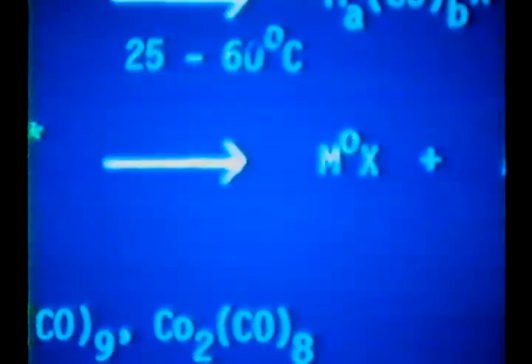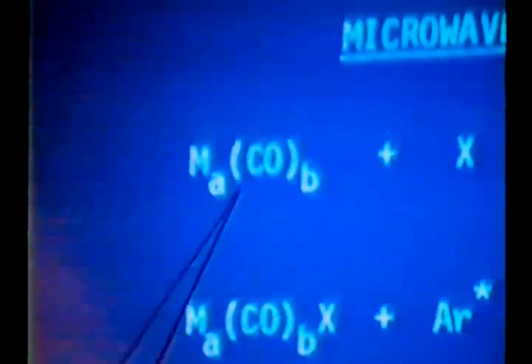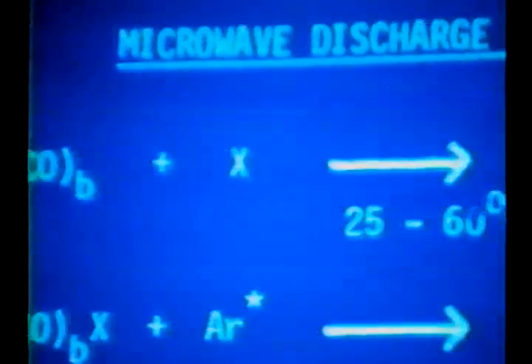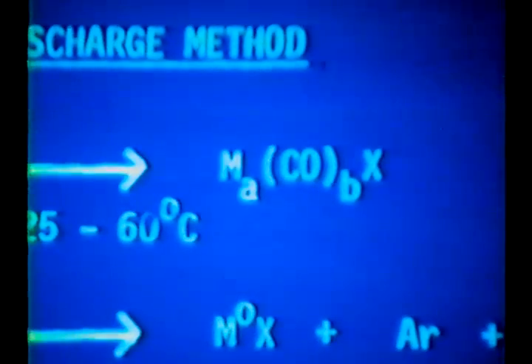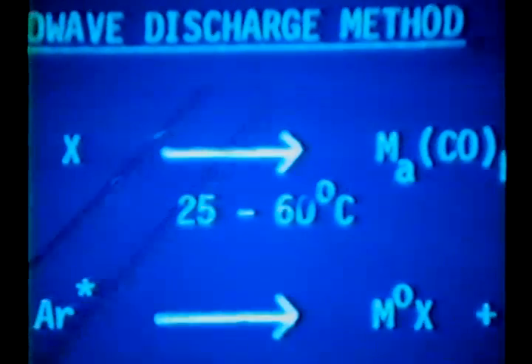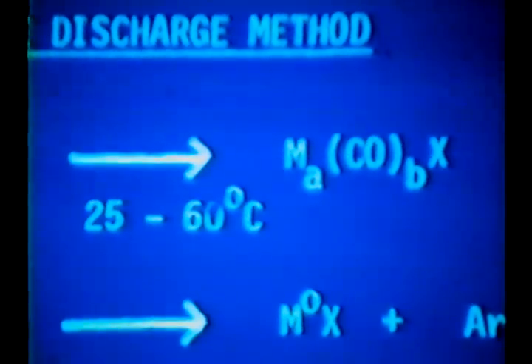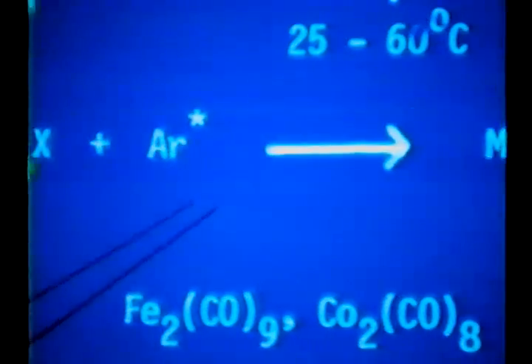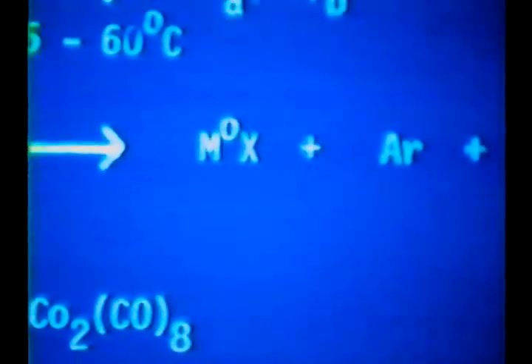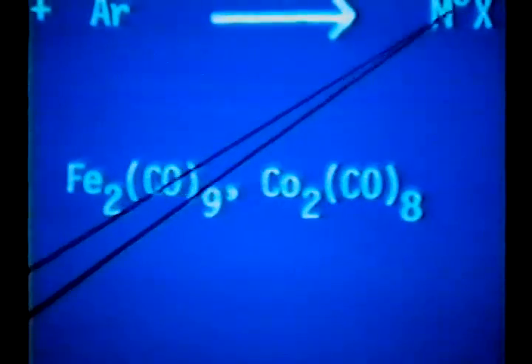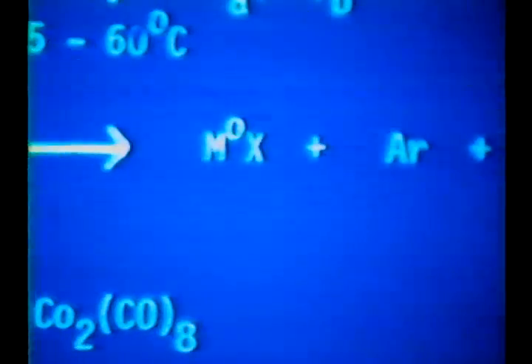On the next slide I have a description of what's going on here. If you take the metal carbonyl, it's usually either cobalt or iron carbonyl dimers, and you may need to heat them a little bit to get them to sublime over onto the zeolite. And then treat this with an argon plasma. These are excited state argon species in the plasma. There are lots of electrons in the plasma. There are lots of interesting species there. What we find is we form very small metal particles in the zeolite, along with argon and carbon monoxide. I'll give you some data for how we believe this mechanism is consistent.